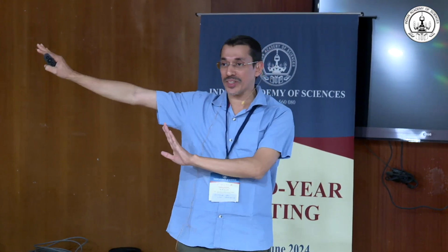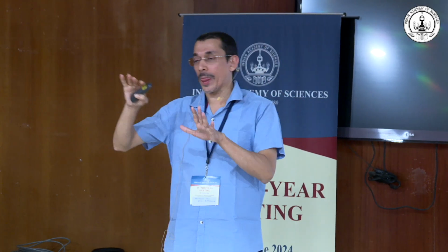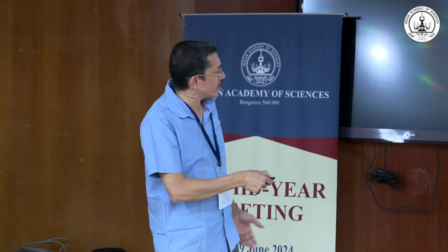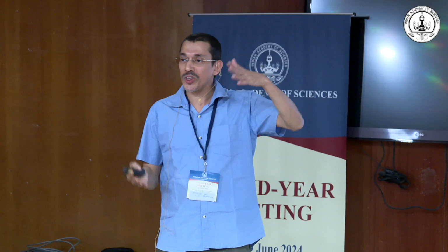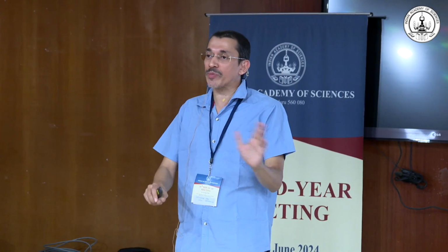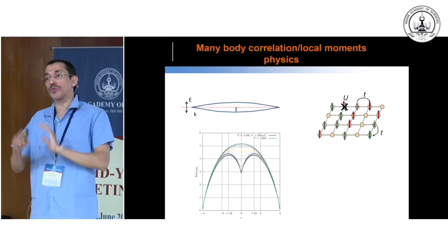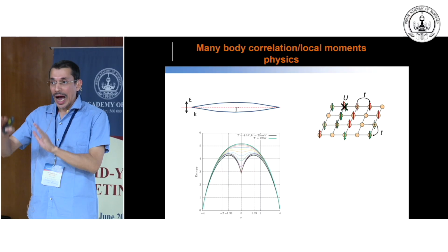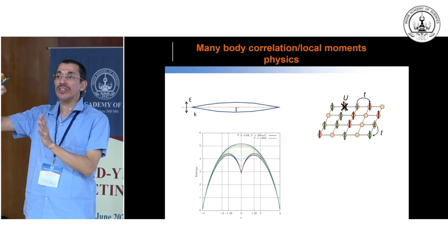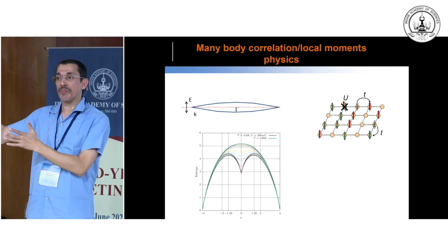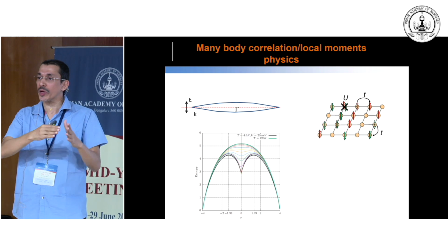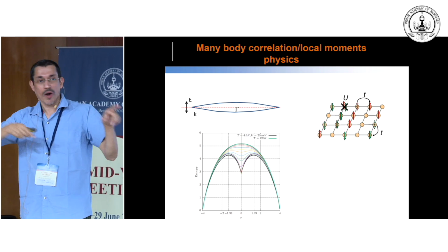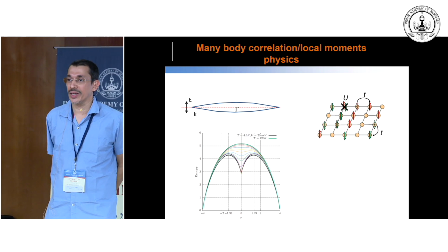But very high temperature, because of this high band, the other bands, they are at room temperature. This is like 10 meV, so room temperature is sort of like 30 meV, so it takes the higher band physics, and at least experimentally we see a spectrum that looks like graphene spectrum, so nothing unusual. The unusual part is up to something like 70-80 Kelvin. Beyond that, the system behaves like graphene-like spectrum, and that makes sense because 80 Kelvin as the bandwidth of this flat band is almost a similar range.